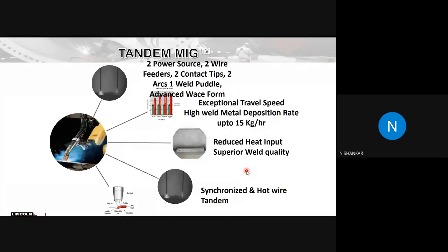How this will help you is to allow you to deposit more than what you can do with a single wire system and increase your productivity. This will give you exceptional deposition, as high as 15 kilograms per hour if you want. It will also give you reduced heat input because it allows you to travel at very high speed, and also gives you superior weld quality.